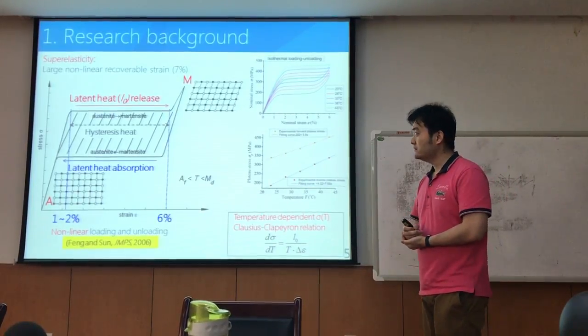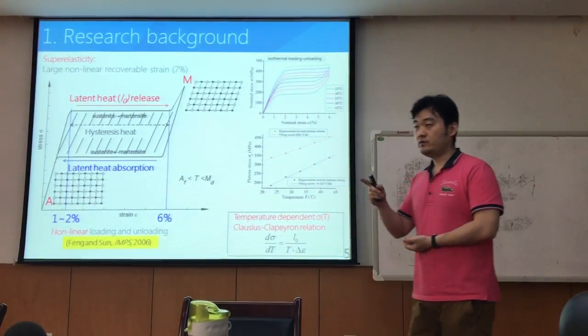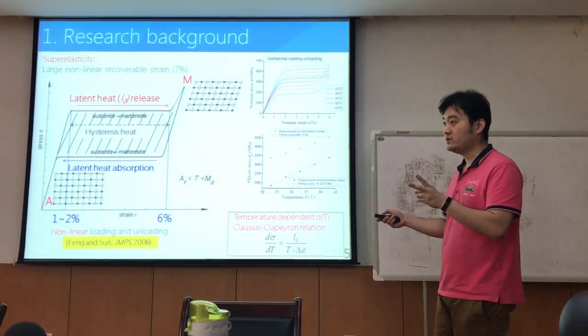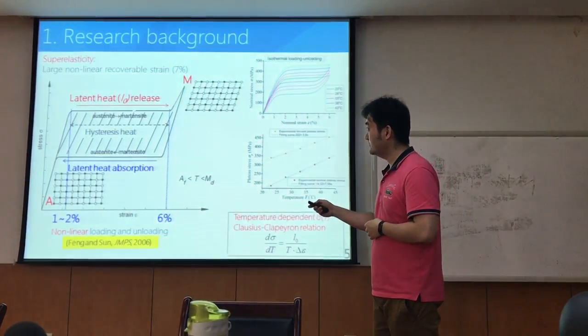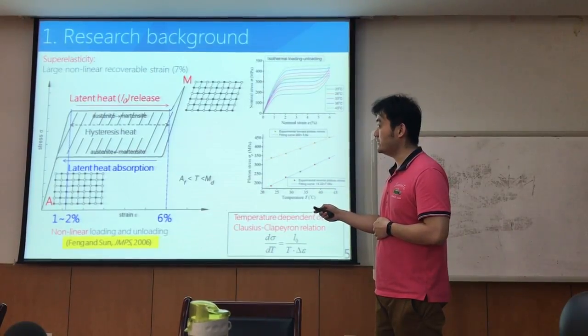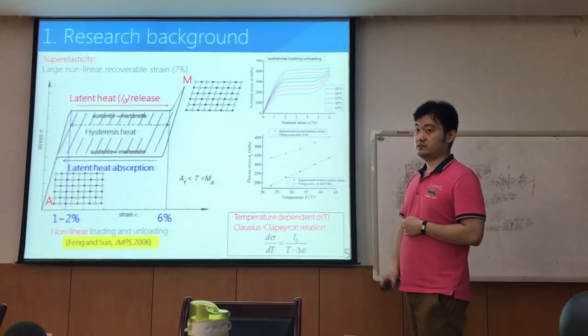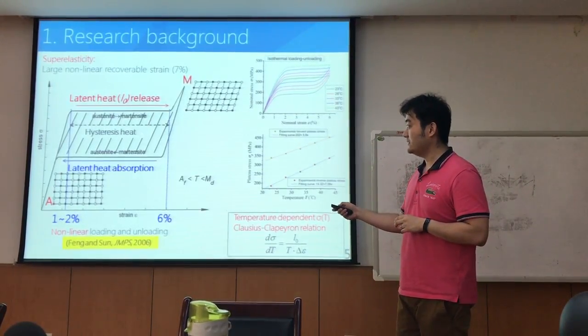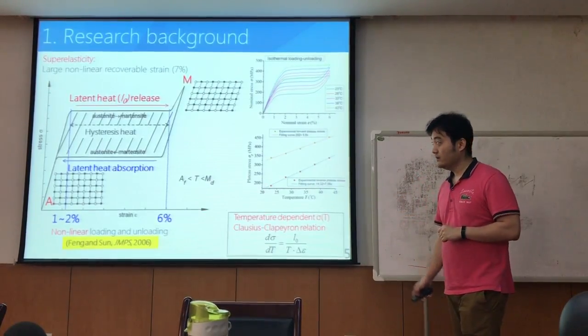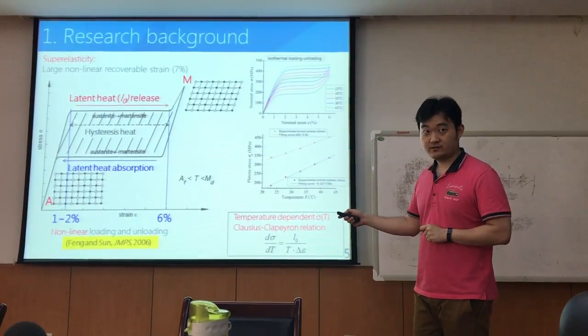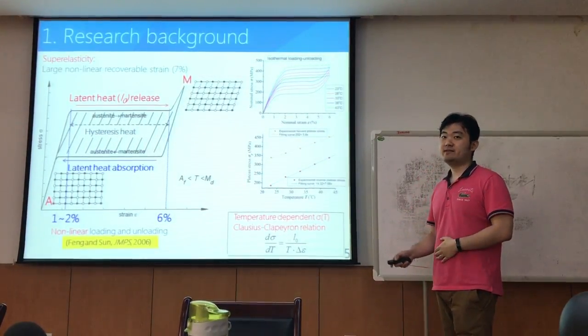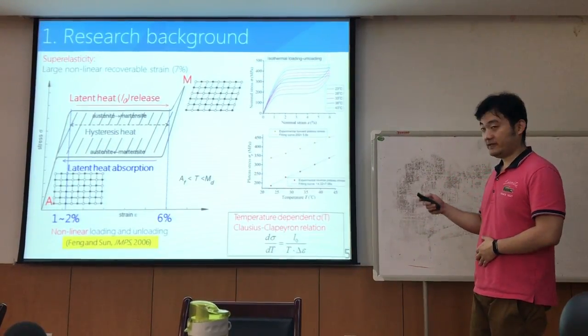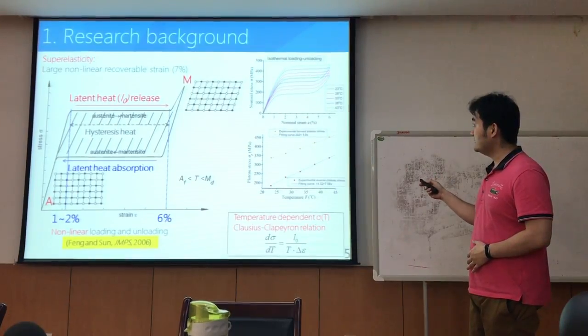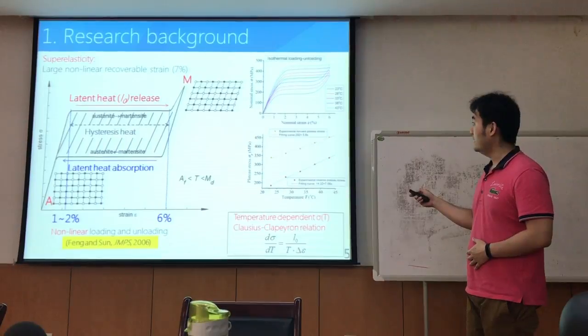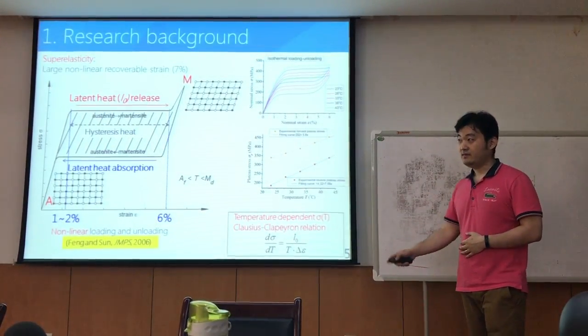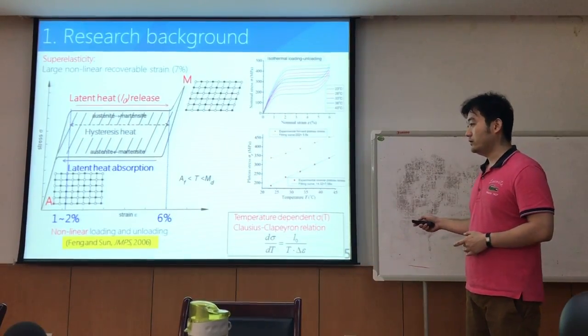Okay. But 2 things we need to focus on. The first one is, during the loading-unloading cycle, 2 heat sources are involved. The first one is latent heat. It will be released during the forward transformation, and absorption will happen during reverse transformation. The second heat source is hysteresis heat. Another important thing is that the stress during the phase transformation, the transformation stress, is highly temperature dependent. Okay, it's a very complicated process. But with the experiment, we can see that under different temperature, their stress strain curves are different, and this is based on the Clausius-Clapeyron relation.